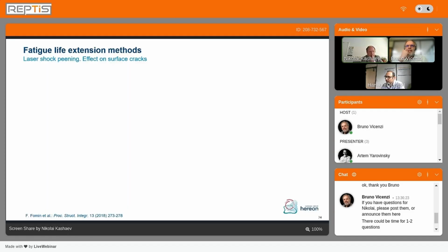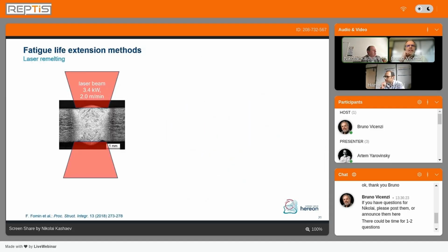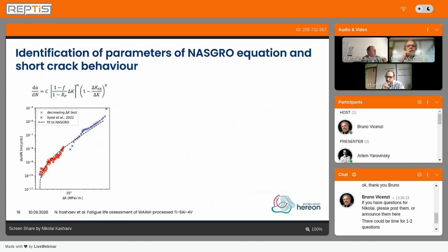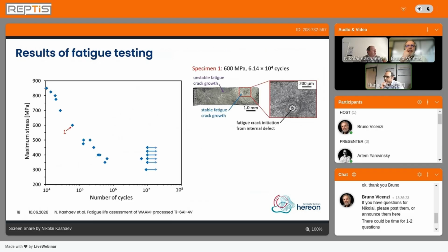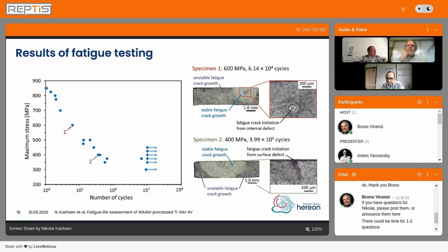I have a question on one of the results of the fatigue testing you just presented, maybe on slide 19 or 20. Maybe just before, there was a stress level versus number of cycles plot. Yes, here exactly. For the specimen that had this WAAM defect at 6 times 10 to the power 4, but for the specimens that survived at 10 to the 7, do they have similar size internal defects, or is it just due to the lower level of stress amplitude that they were exposed to?